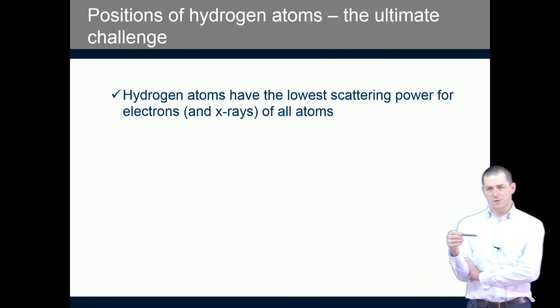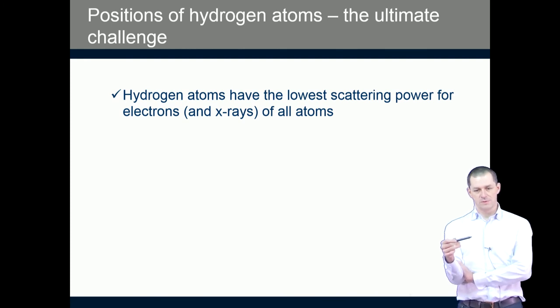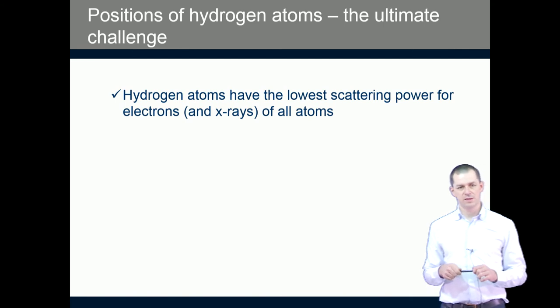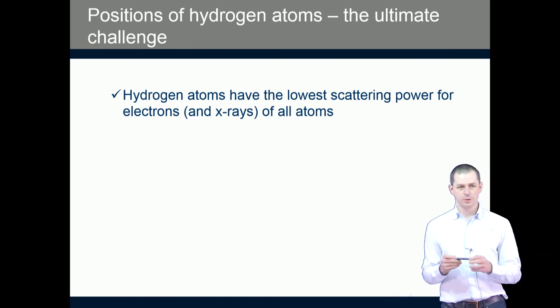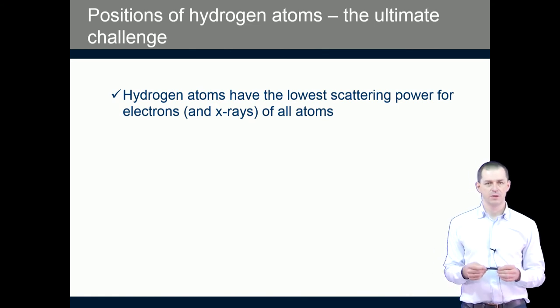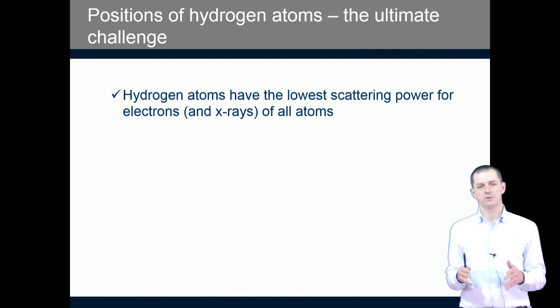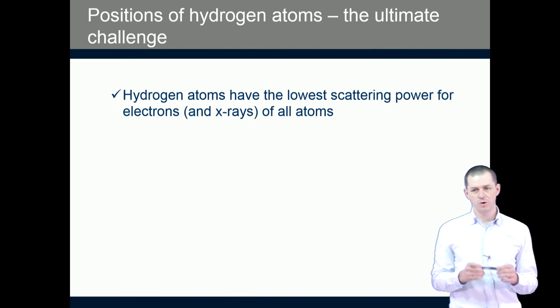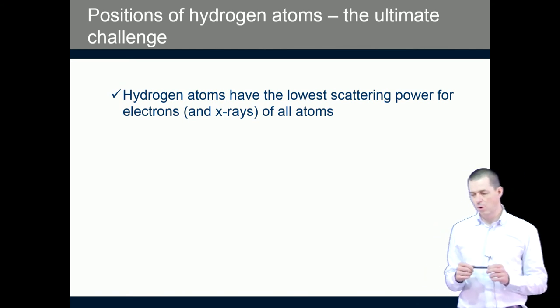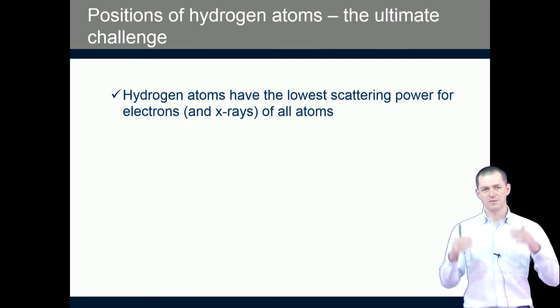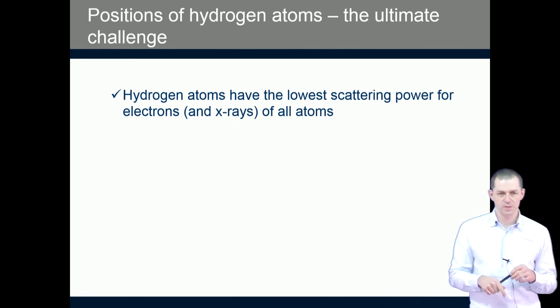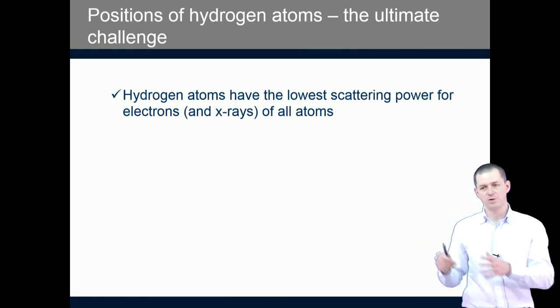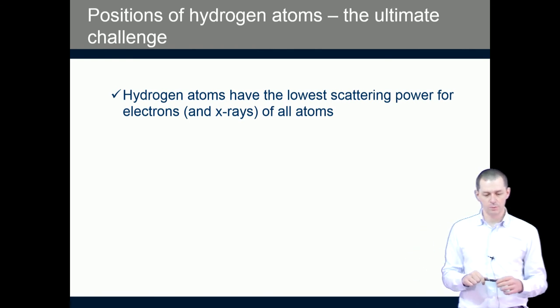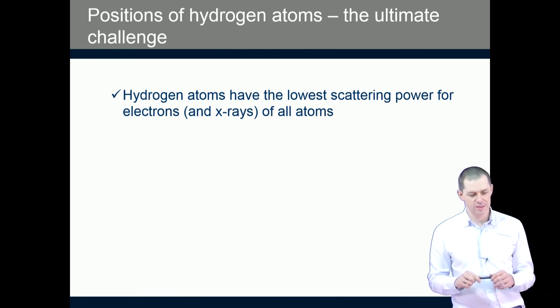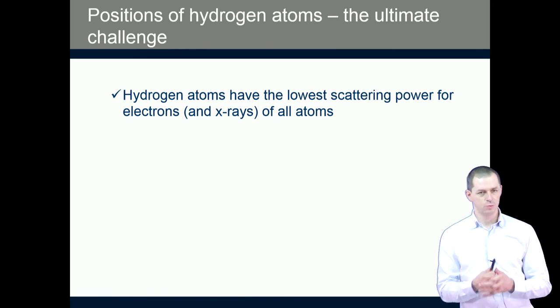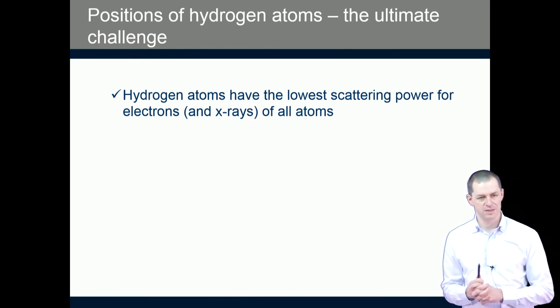The reason to get a good description of the structure, of accurate fit of intensities to the experimental intensities, is not only to get accurate positions of atoms, because I can imagine that for some applications getting the positions accurate to 0.1 angstrom may be enough. The reason is also to get more sensitivity of the result to fine structural features, like sensitivity to atomic type. If you exchange two atoms with close number of electrons, you want your refinement to be sensitive and to tell you which of the two are the good ones. Or if you have some disorder or partially occupied atomic position, you want to see that and you want to be able to describe these partially occupied sites.